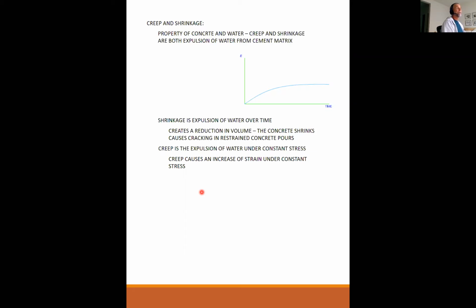But creep keeps it deflecting, and it deflects a lot more in the first weeks and months, and then it just keeps on deflecting over a period of several years until the increase in deflection due to creep over, say, maybe 3 to 5 years is barely noticeable anymore. But it will cause a beam that maybe has a 1/2 inch deflection the day you kick the forms out, and then you come back and you revisit it in 3 to 4 years, and that 1/2 inch deflection, oh my, now it's 2.5 inches of deflection. That can happen from creep, and it's something that we have to keep in mind. Any questions on creep and shrinkage?